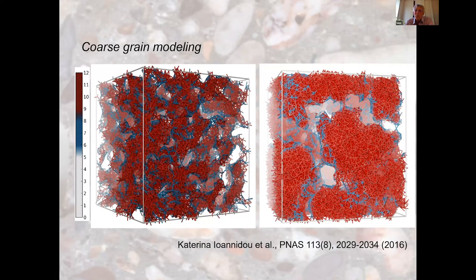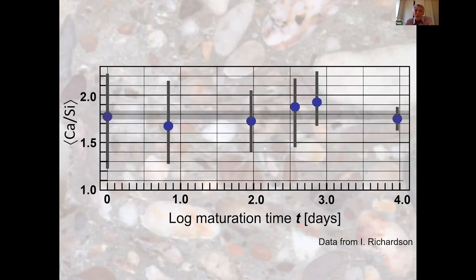Let me just point out two observations which I always found very unknown and not understood. One is the composition of the real glue of concrete, which is CSH or its aluminum-rich version. Here is a plot of the calcium to silicon ratio as a function of the aging time of a cement paste, from a few days to more than 40 years. And what you see, as we all know, is that the calcium to silicon ratio is rather constant, with an average of about 1.7.